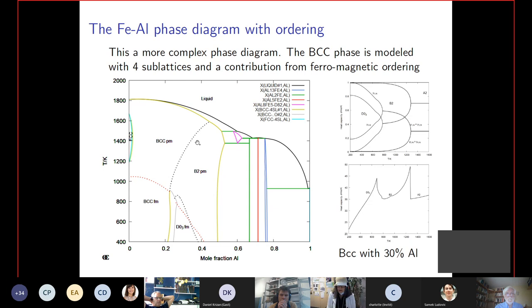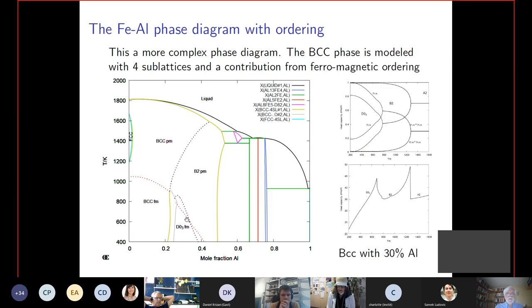And if you look more in detail, if you take 30% of aluminium in the BCC structure and calculate varying just the temperature, you can see the different ordering here. This is the DO3 structure, where you have mainly iron in one sublattice, you have a little less iron in another sublattice, and you have two sublattices with mainly aluminium. And then at some temperature here, the DO3 structure is gone. Well, you have a magnetic transition here.